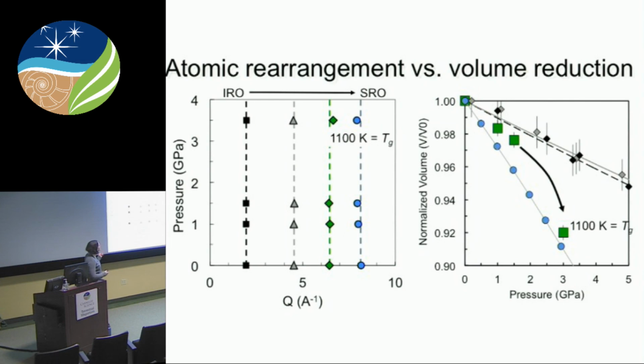This is an example for an enstatite composition glass. Here you have normalized volume, so the compression curve, with density increasing down as a function of pressure. The blue curve here is silica. These dots up here are forsterite, all cold compression. And the green squares are my tomography data. What you can see is that enstatite composition is intermediate to forsterite and silica. That all makes sense on compression. But then when you heat it, you get this really large volume reduction. This is an 8% volume reduction at the glass transition.